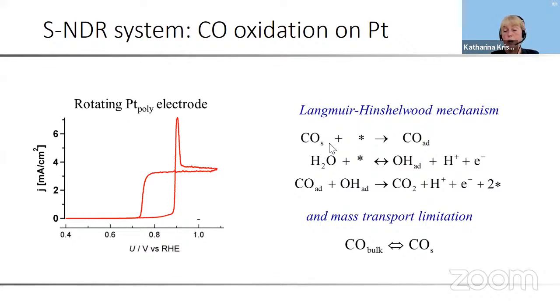So CO dissolved in front of the electrode adsorbs on the electrode surface. You oxidize water to give adsorbed OH, and these two species finally can react to CO2, which desorbs immediately. The feedback process also requires diffusion of carbon monoxide from the bulk to the surface. So these 4 reaction steps together give a positive autocatalysis.